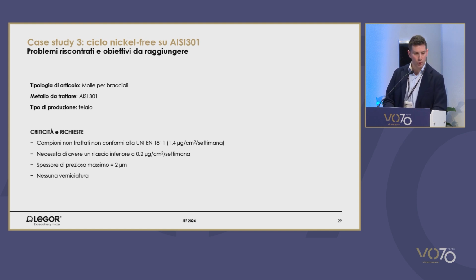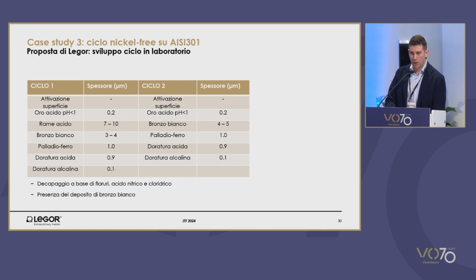The precious metal shouldn't be thicker than 2 microns and shouldn't require any painting. 2 cycles have been tested in the lab. The activation of the surface was similar to the ones that we've seen earlier, and the adhesion was promoted with the acidic gold plating. The new item is white bronze layering. These white bronzes usually include cyanide, and in the field of eyewear, they are not well tolerated. In this case, this is an accessory we're talking about, so we didn't have any problem using cyanide. The difference between cycle 1 and cycle 2 is that cycle 2 doesn't include acidic copper.